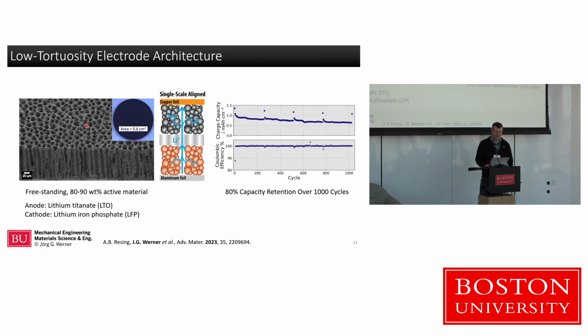And we tested these, especially with materials like lithium titanate and lithium iron phosphate, because they're very stable chemically, so we can really hone in on what is going on with the structure, rather than having to think about the chemical stability of the material. So we like to use lithium titanate as an anode material, lithium iron phosphate as a cathode material, because they're chemically very stable. And we've shown that we can cycle these for 1,000 cycles and keep 80% of our capacity, which is really a benchmark that you want to hit, and these materials are fine, and the structures are fine, most importantly.